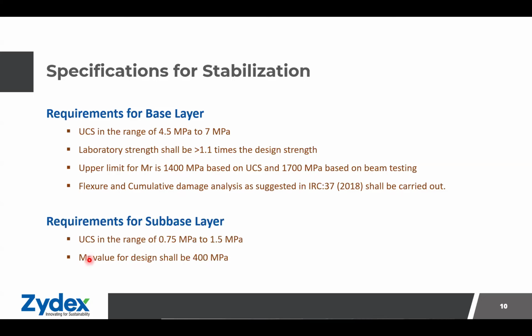For the subbase layer, the UCS needs to be in the range of 0.75 MPa to 1.5 MPa, whereas the modulus value shall be 400 MPa for the design.